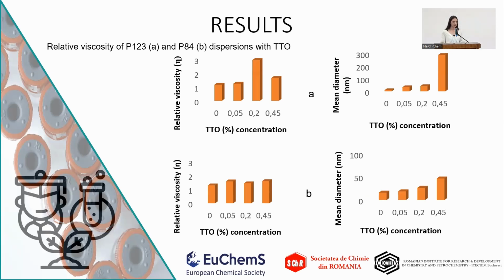The relative viscosity of all the systems was measured. The viscosities are lower than usual, as expected, because of the small concentration of pluronic dispersion, which is 1%. Again, there is an exception in the case of the P123 system, which has a slightly higher relative viscosity. From other studies in the literature, we concluded that this increase in relative viscosity may mean the transition from a spherical shape to an elongated shape, just in the case of the P123 with the TTO. From the rest of these graphs right here, we can say that, again, it confirms that we encapsulated the essential oils, as the concentration increases proportionately with the mean diameter of the aggregate.